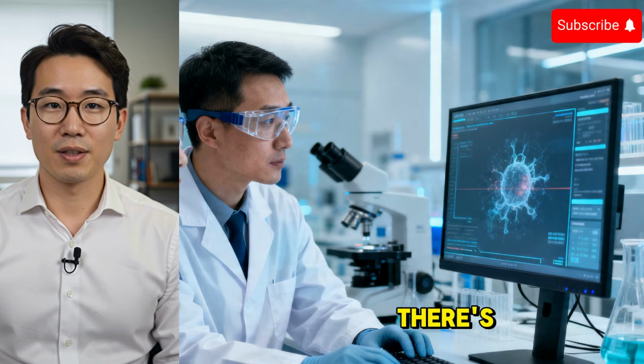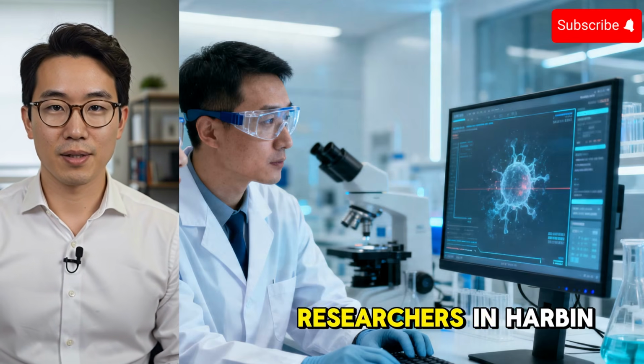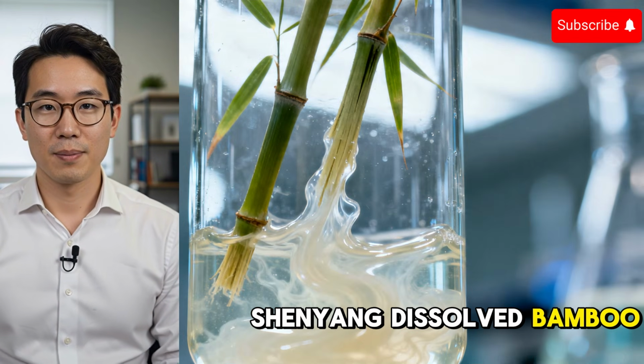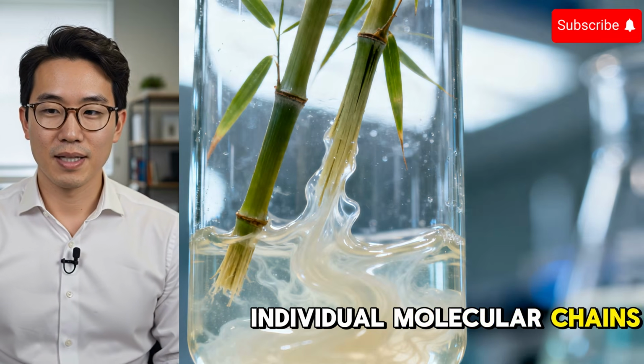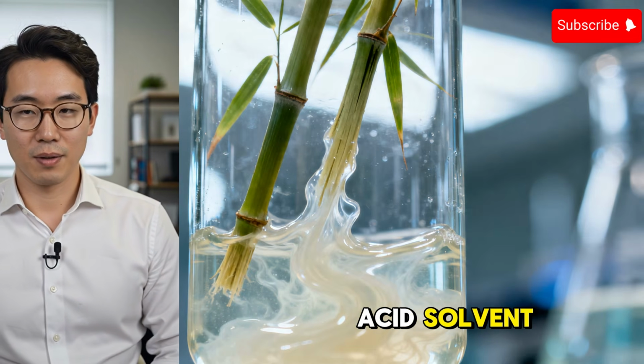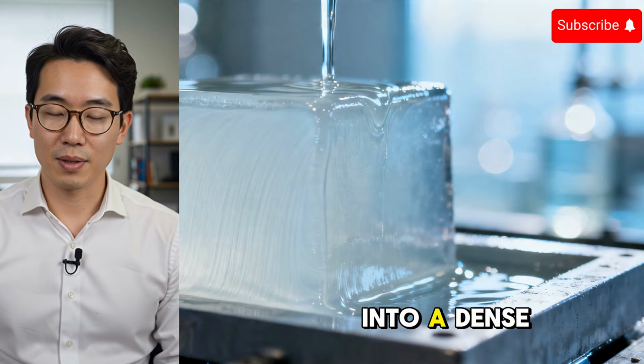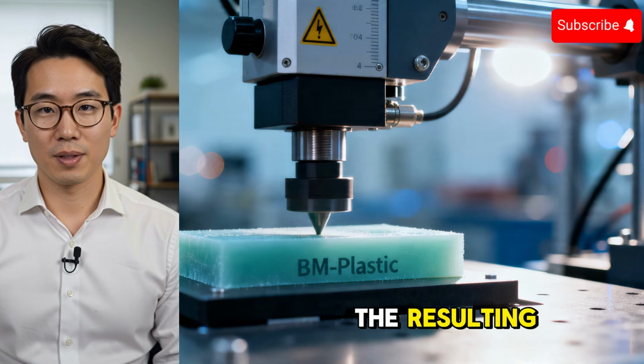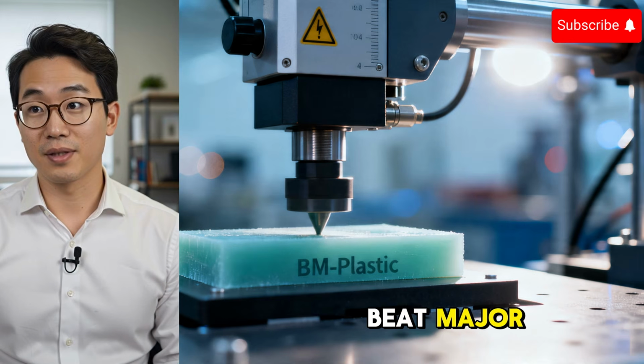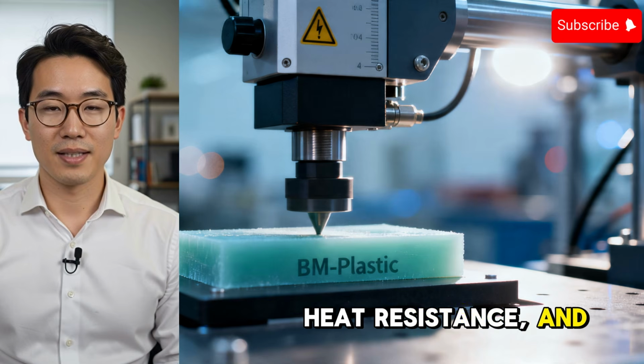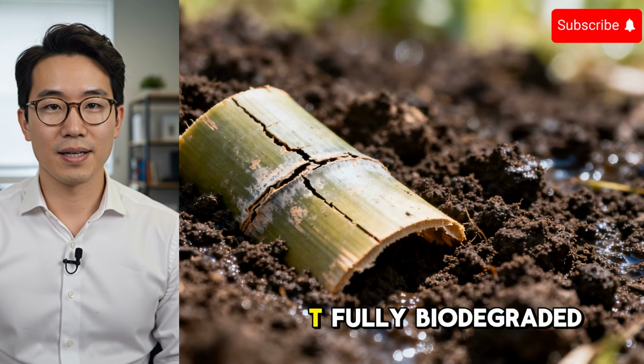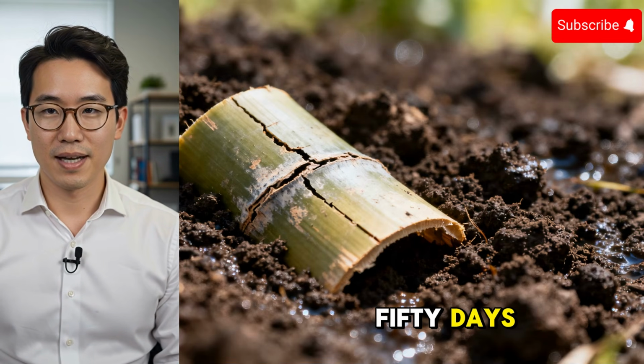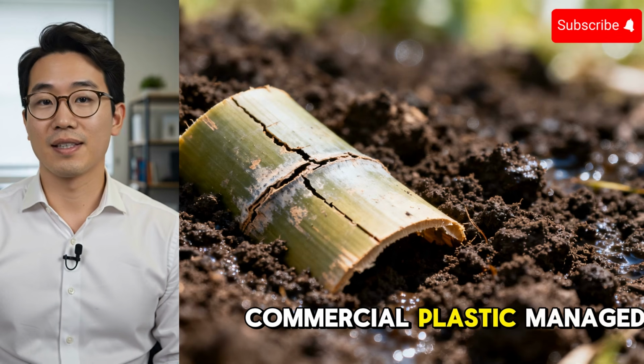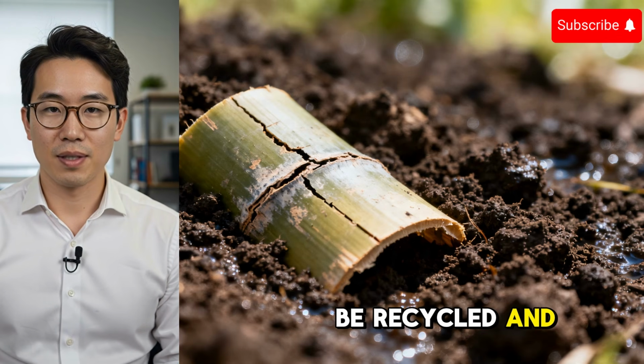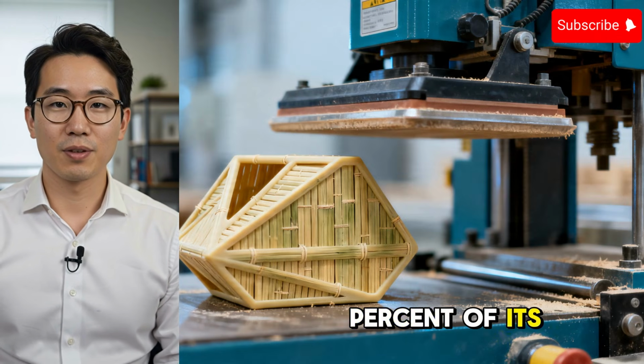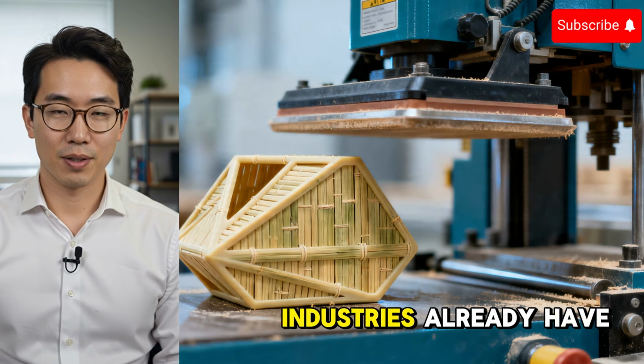Quick recap, because there's a lot stacked up at this point. Researchers in Harbin and Shenyang dissolved bamboo cellulose down to its individual molecular chains using a zinc chloride and formic acid solvent, then rebuilt those chains into a dense new structure using ethanol. The resulting BM plastic matched or beat major commercial plastics in strength, heat resistance, and impact toughness. It fully biodegraded in soil within 50 days, something no comparable commercial plastic managed. And it can be recycled and reshaped while keeping 90% of its strength, using manufacturing equipment industries already have.